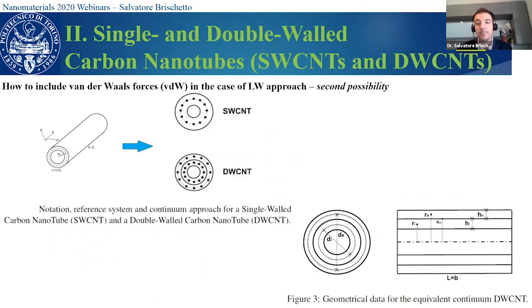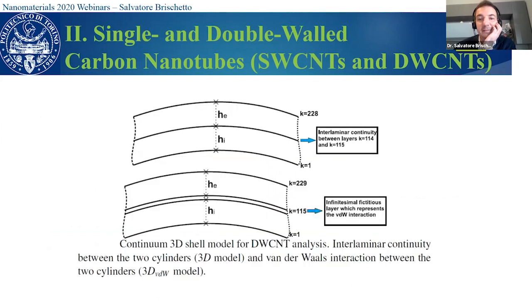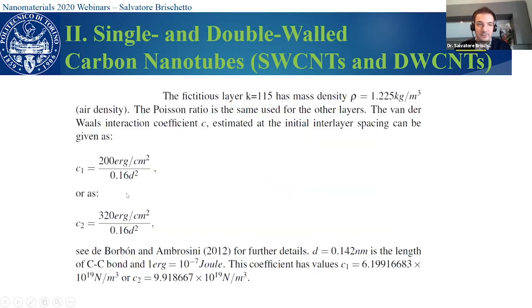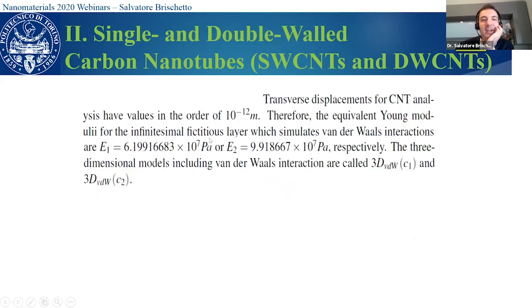Another possibility, a second possibility, is to introduce a fictitious layer, a very thin fictitious layer, which represents the van der Waals interactions. So the two nanotubes are separated, very close between them, and they are separated with this fictitious layer, which represents the van der Waals interactions. So in order to calculate the elastic properties of these fictitious layers, we start from the van der Waals interaction coefficient, and then we arrive at appropriate values of Young modulus to give to this layer.